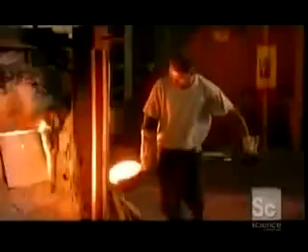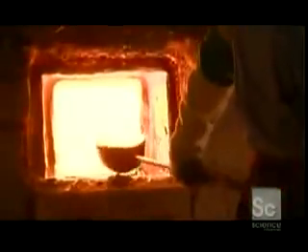With only seconds to spare, they hurry to the mixing table, keeping the glass in motion to prevent it from cooling unevenly on the way. It's critical they cool off the ladles between each use, or the next scoop of glass will adhere to the ladle surface. The ladles they use vary in size, holding between 4 and 40 pounds of molten glass. Workers pour as many as 5 different ladles at once to make a single color.